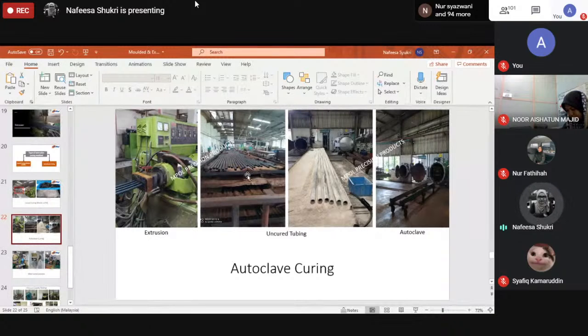One is just roughly put in a tray, and for the next one we need to put some talcum powder. This difference is because of the rubber tubing size. For example, for that one we don't put any powder because the tubing size is small. So when we put it in the autoclave, the size can stand. We call this stability of size. The rubber tubing doesn't collapse.